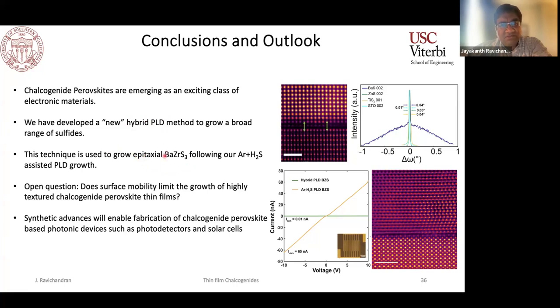We've grown epitaxial barium zirconium sulfide using argon and H2S, and also now using the hybrid PLD technique. There are still some open questions, some mechanistic questions about how these things work. We have used RHEED to a limited extent to learn a little bit about it, but I think more in situ characterization is needed. In an unrelated work, my group has developed or improved on some of the existing in situ Auger electron spectroscopy techniques for oxide thin films. We anticipate that could help, and maybe adding a little bit more in situ characterization will allow us to gain better insight into how to grow these materials better.